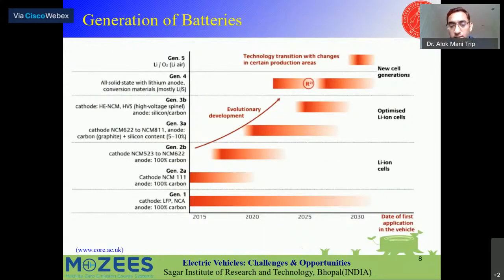So if we see the generations of batteries, this is very important because the research is following this trend. In the first generation of the battery, the cathode was LFP, lithium iron phosphate, or this NCA cathode, and the anode was 100% carbon. Okay, then the second generation came for the batteries. This has the NCM, nickel, cobalt, and manganese 111 system with 100% carbon anode. Then the next generation came, where other compositions of nickel, cobalt, manganese oxide based systems were used, with different compositions 5, 2, 3, and then 6, 2, 2 ratios.